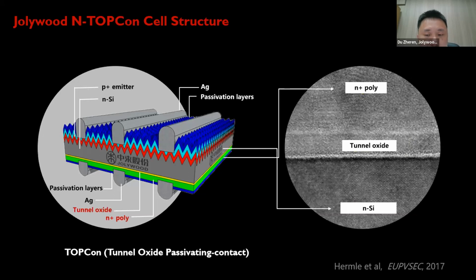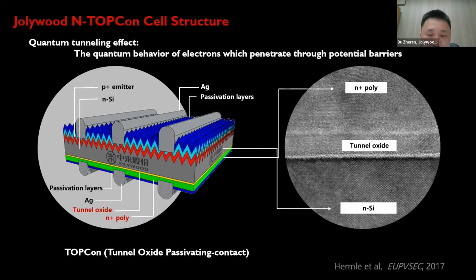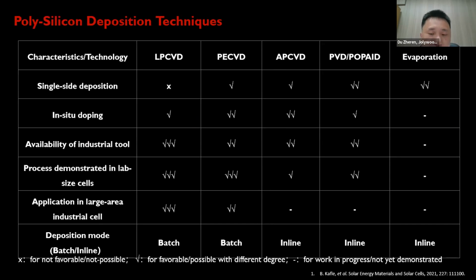The oxide has very high selectivity. It allows the majority carrier to tunnel through the oxide at very low junction resistance. The structure takes advantage of the quantum tunneling effect, which is the quantum behavior of electrons which penetrate through the potential barrier. So all these properties enable the cell efficiency beyond 25%. Since the doped polysilicon layer is the key structure of this TOPCon cell, we will investigate in more details regarding the poly deposition and the doping methods.